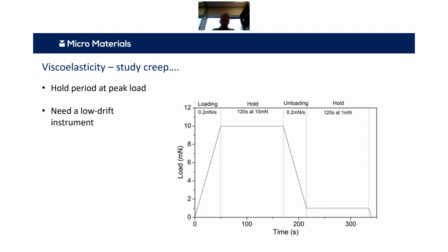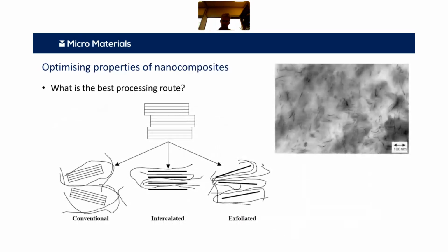It's very difficult to separate out, for highly viscoelastic materials, the effects of creep, creep recovery and thermal drift. So it's preferable to have a low drift instrument like the NanoTest to do these tests rather than try and correct things out. So if we take this experimental protocol and apply it to polymeric nanocomposites.